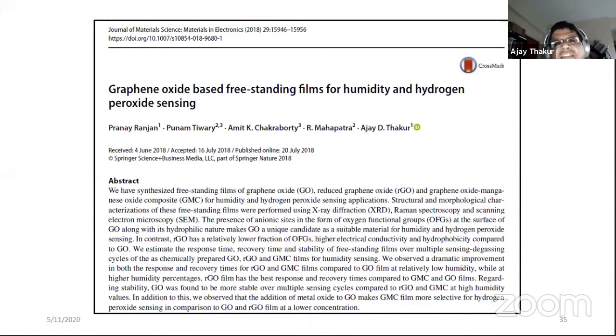So soil moisture testing is something which is a very crucial requirement for a large class of people, including farmers in particular, considering the large volume requirement for such kind of sensors. In addition, for environmental monitoring in closed spaces, humidity sensing is crucial. What we found out was graphene oxide freestanding films were very good at sensing humidity selectively under appropriate compositing with suitable transition metal oxides.